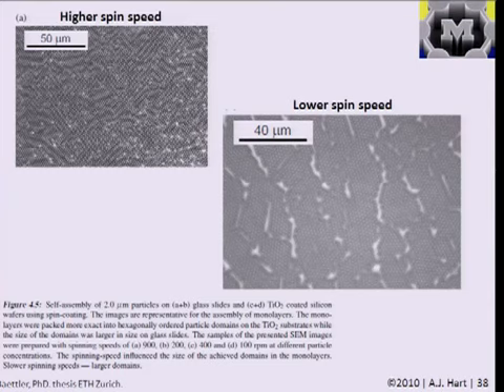So in the bottom right case with a lower spin speed, there was, you could say, more time for the layer to become well packed. And although in both cases you have these sort of separated domains, kind of like particle grains, here the domains are much larger in the bottom right case than in the top left case. You may say that you moved the same amount of liquid over the surface in both cases, but in the top left case you moved it too quickly and didn't give enough time for the particles to reach a more highly ordered state. And it's possible to do this over very large areas.